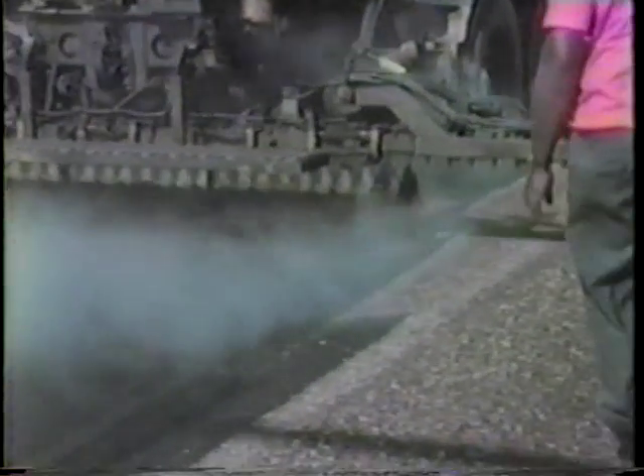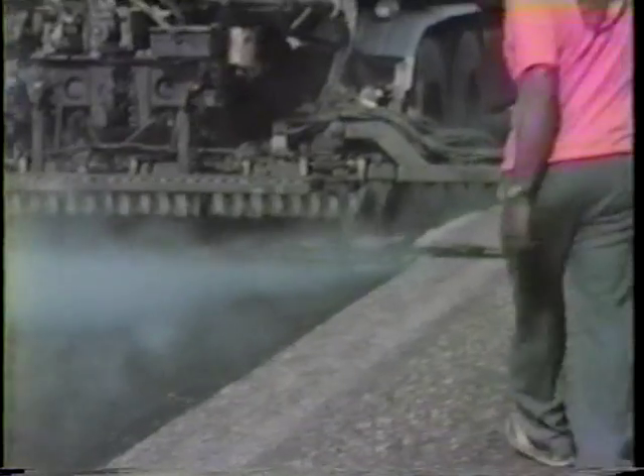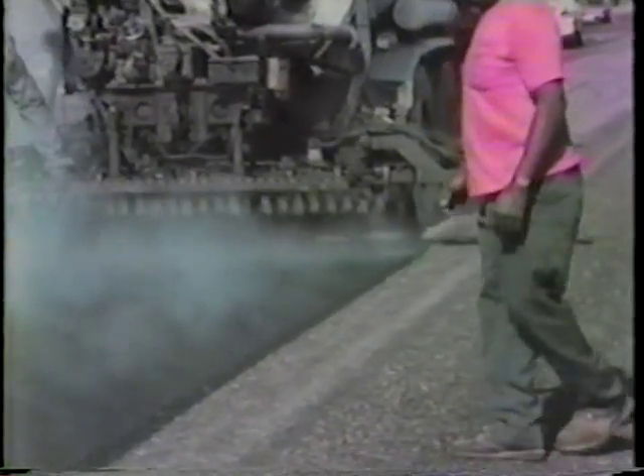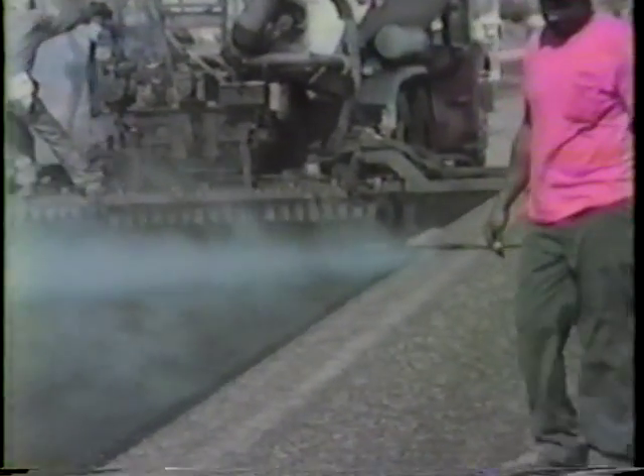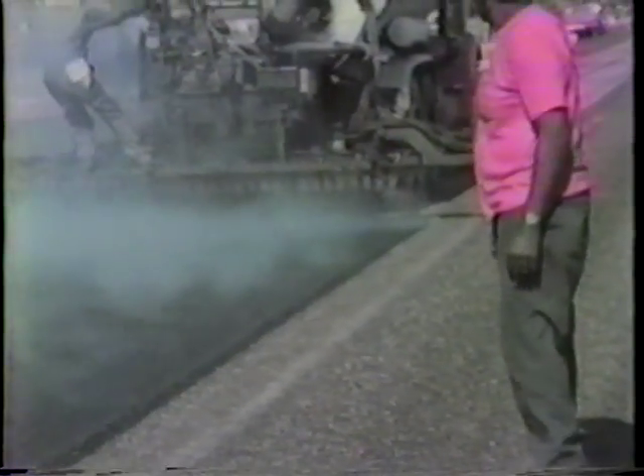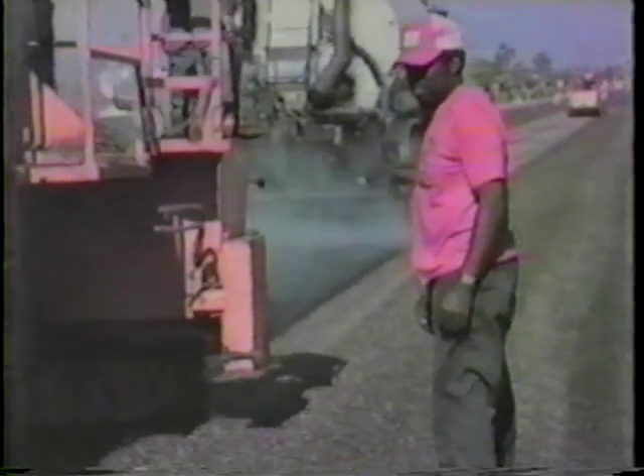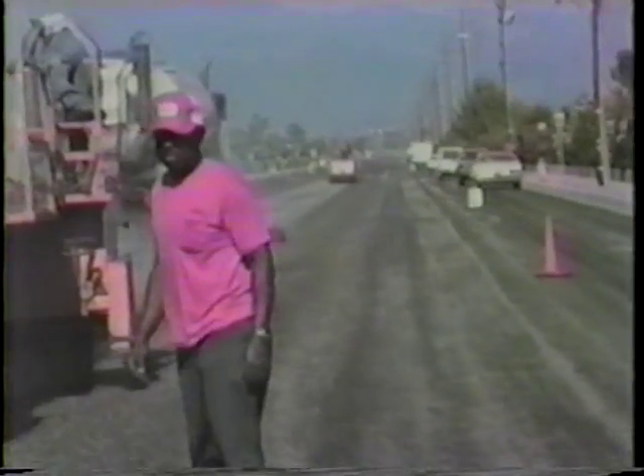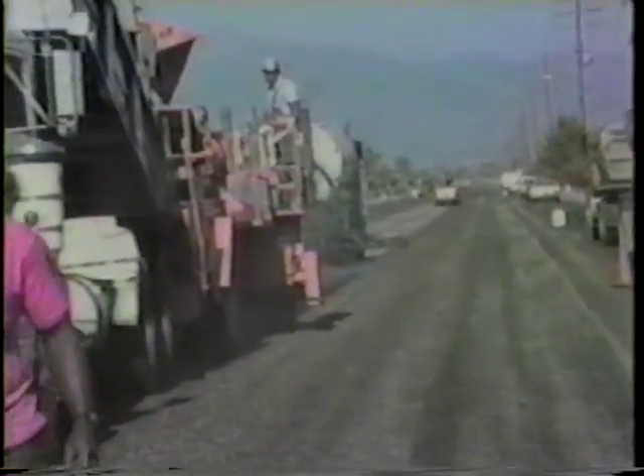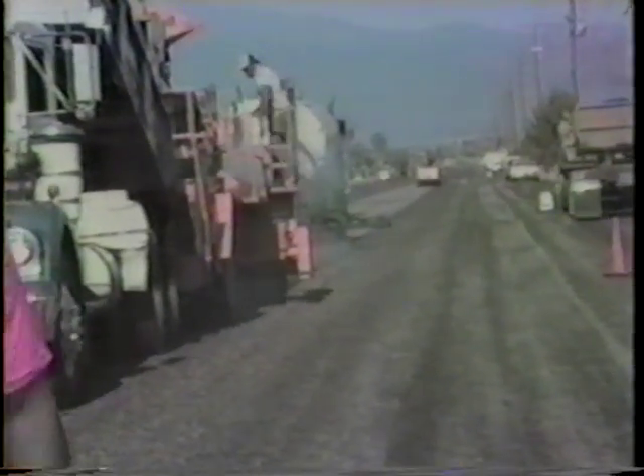Double SAM chip seals are applied when pavement surfaces are extremely rough. A large cover aggregate is placed on the bottom layer and a smaller cover aggregate on the top course. SAMs provide a lasting, waterproof, skid-resistant, durable surface which thwarts oxidation and flexes to conform with movements of the surface. Using asphalt rubber in a SAM improves and extends the serviceability of asphalt pavements which are experiencing extensive cracking.